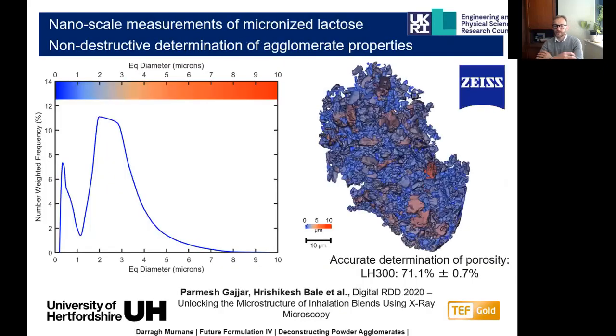And when we do this, we're able to pull out a particle size distribution, which we see on the left here. And we can see that there are particles which are down as low as 200 nanometers, but the bulk of the particles are within the range of about 2 to 3 microns. So previously, if we'd sized this, we would have seen particles with a 2 to 3 micron size, but because of the XRM, we're able to now look at the individual agglomerates and see that they're roughly 70 to 100 microns in the length dimension, but that's composed of a high number of individual particles.